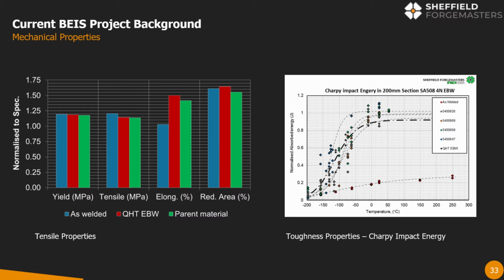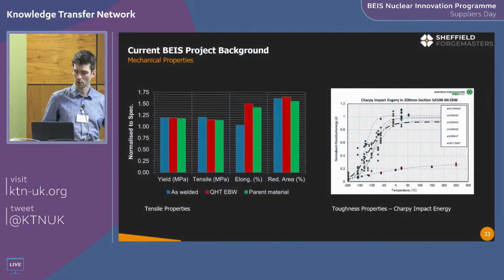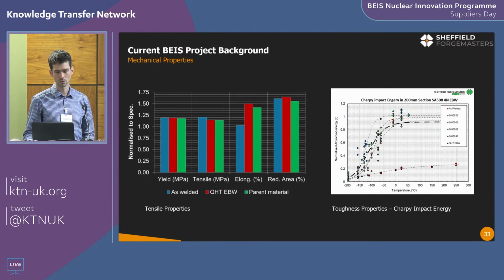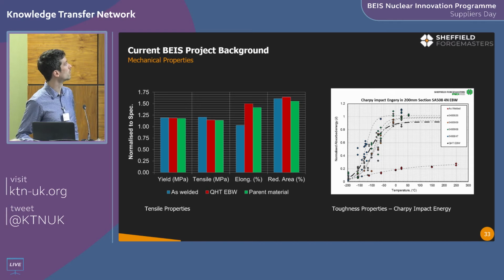So we could produce defect-free welds very quickly in a single shot, and via heat treatment in thick section, we were able to get parent material properties back. So it was a successful project, but the issues we drew out of that were that the equipment and the local vacuum systems weren't up to surviving the longer weld times that the larger size components we require to manufacture would need.